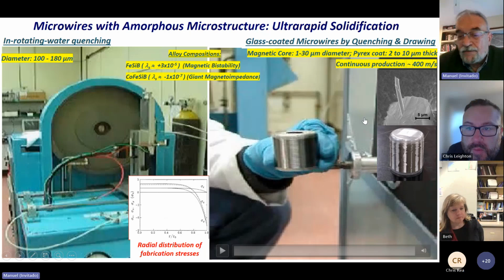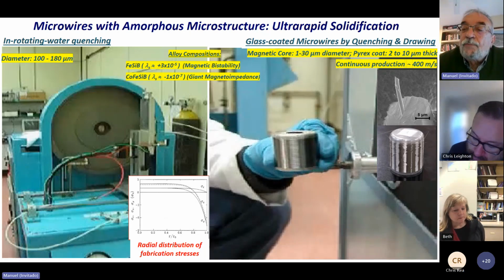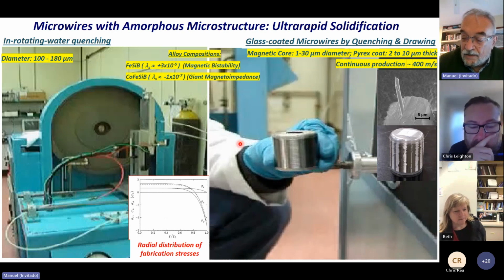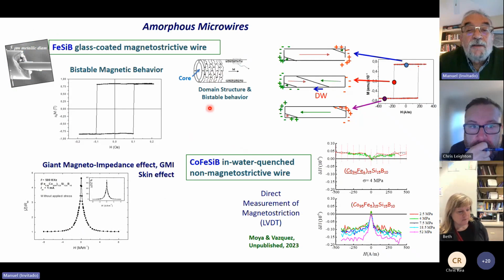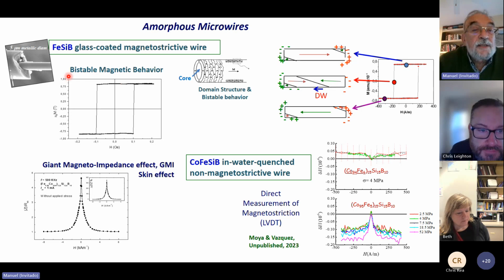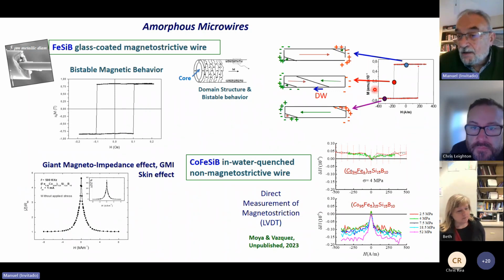So in the process of fabrication, we are able to obtain the microwire, which is going to be characterized and used in sensors later. So the main properties of these two families of microwires, those with large magnetostriction, have bistable magnetic behaviors characterized by a square hysteresis loop. It is practically impossible to get an experimental point in this giant Barkhausen jump, and this is interpreted with this schematic loop in the upper part to the right.